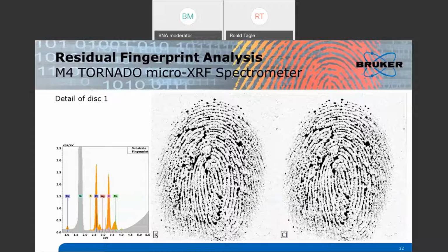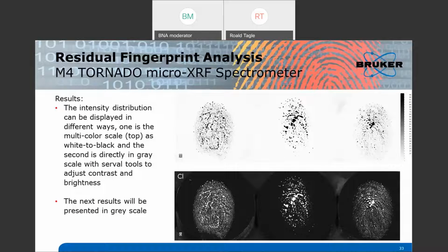And if we compare, for example, in order to get a feeling about how strong the contrast is between the glass and my fingerprints, you see that on the spectrum at the left side. So basically, you see the silicon peak for the quartz disk, and on top of that, you see the contribution of the contrast element. The strongest peaks are basically the potassium and the chlorine peak, and you have a small peak for calcium and an even smaller one for sodium. But basically, this is the element sensitivity contrast that we can achieve with the machine for this kind of application.